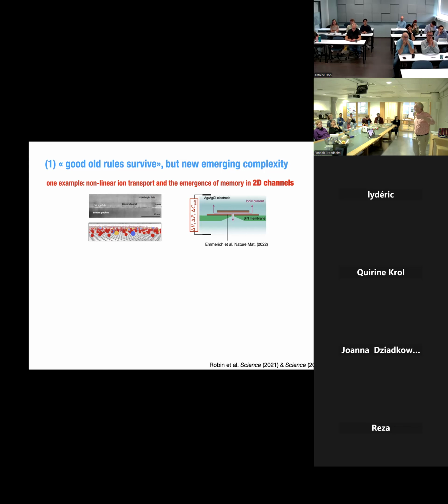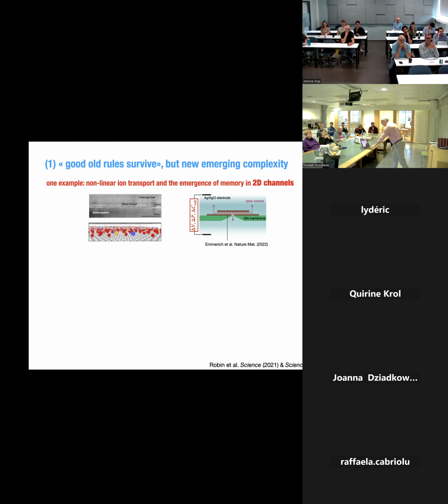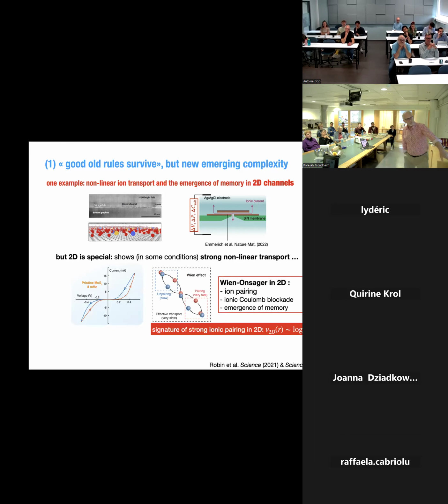And just to give you one example, we did a lot of experiments where we measured the ion transport across these very tiny channels, a few angstrom in thickness. Usually it behaves very nicely in a simple way, like the electric current is proportional to the voltage, so you have a conductance. But in some cases, you start to see a response like that. So this is current versus voltage. Actually, this is done in a molybdenum disulfide system, which is insulating. In this case, it can also be conducting, but here it's insulating. And here you see you have this kind of very nonlinear response.